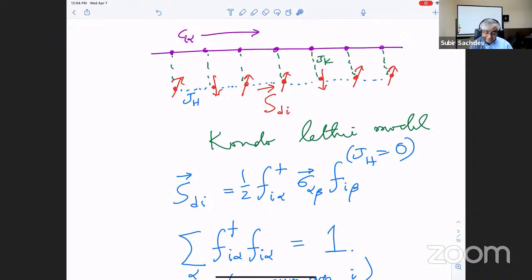All right, so we're continuing our discussion of this model called the Kondo lattice model. It applies to many interesting compounds, sometimes called heavy fermion compounds. They typically have a heavy element like cerium or uranium, where the active or unpaired electrons are heavily localized, and that's what we represent by the spins. And then you have conduction electrons, or mobile electrons, that are typically from s-p bands or d bands of lighter elements.